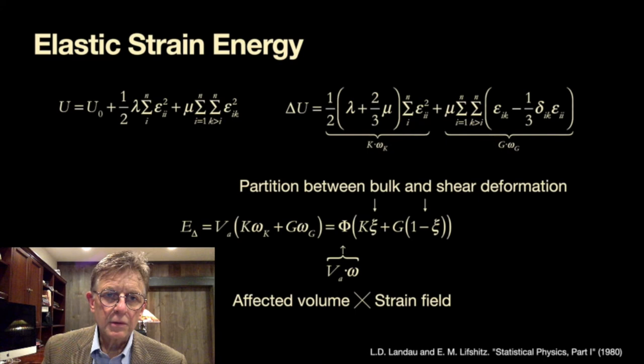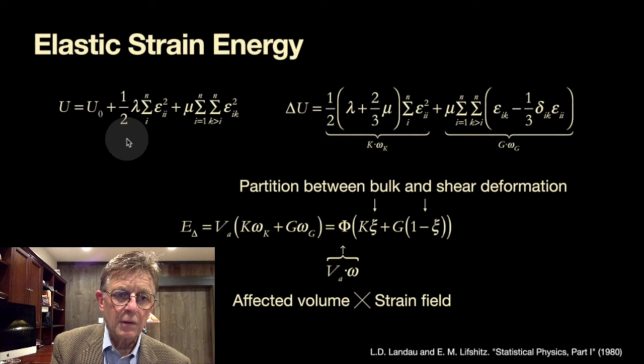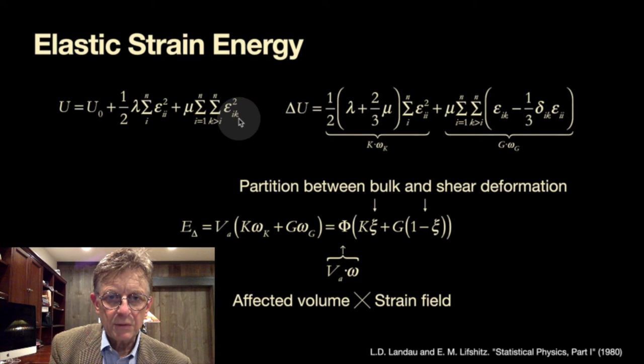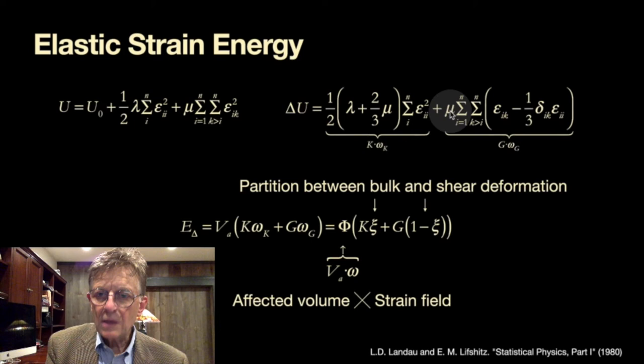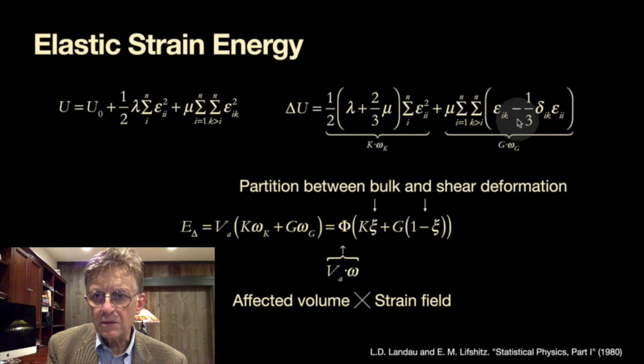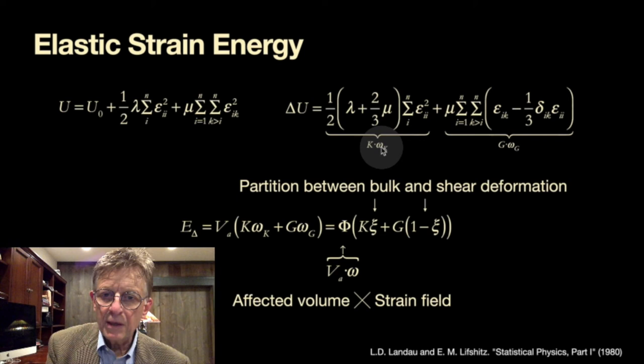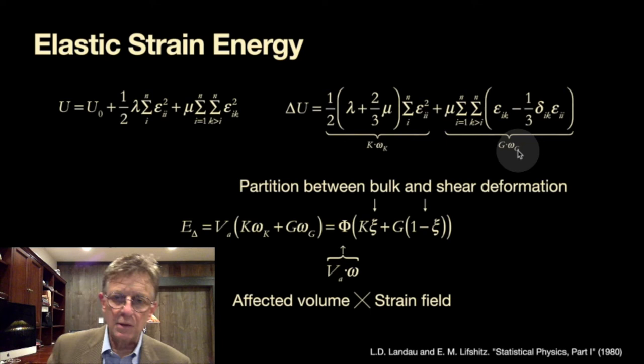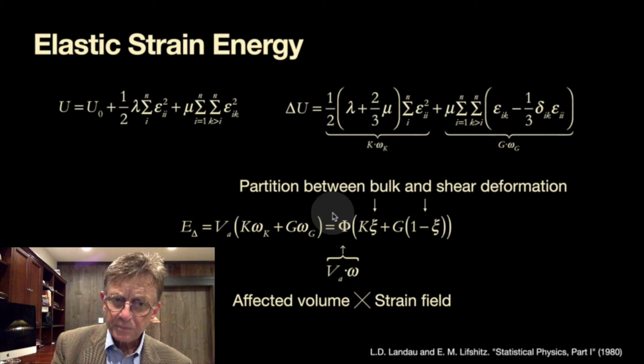And they're very closely linearly correlated. That is not a surprise because the more compact the structure is the lower the energy is at the bonded side or the equilibrium side and therefore overcoming that, dislodging from that requires a higher activation barrier. Now the important thing to notice that the total amount of the Coulomb energy to the total activation energy, the measured one, is only six percent. This means that the other 94% of this activation energy belong to the strain deformation. And so here we write the equation from Landau and Lifshitz of the strain energy which involves the two Lamé constants lambda and mu and then these strains here are the sum of all diagonal terms and these are the double sums of all the off diagonal terms.